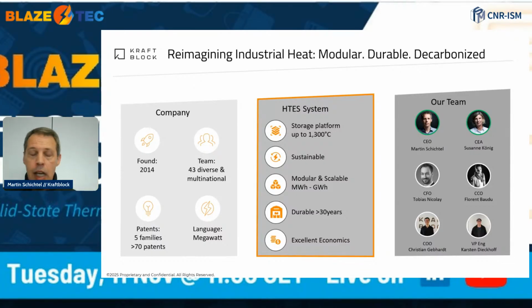Modular and scalable, that's not a nice to have, that's a must have today. Because in most of the applications you will see in the market, these are brownfield applications. So you need to adapt to the local footprint, you need to adapt to the process of the customer, which cannot be served by one standard solution. So we try to create a product standard for the customer and not try to customize or standardize our customer to our product. Durability, even before we released the first proof of concept, you will see it a little bit later, we fully tested our material and the storage itself for 15,000 cycles charging between 200 degrees C and 1,200 or 1,300 degrees C with nearly no degradation.